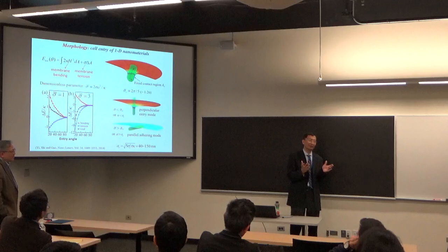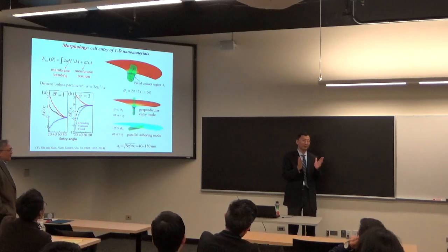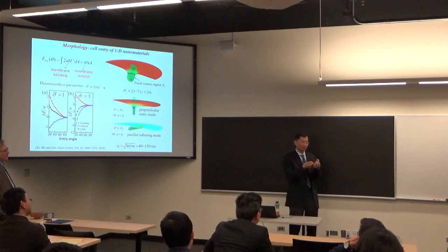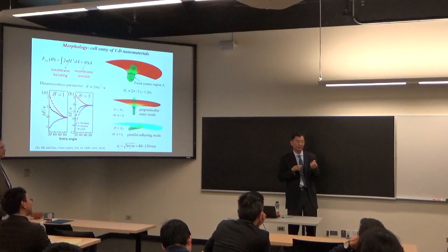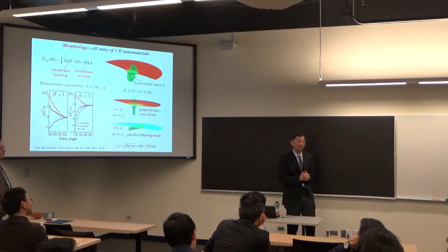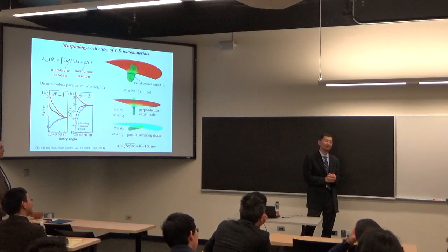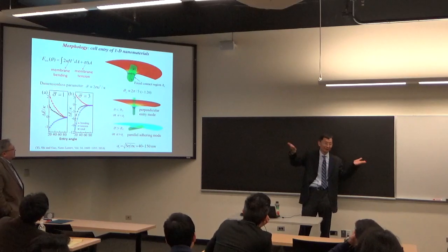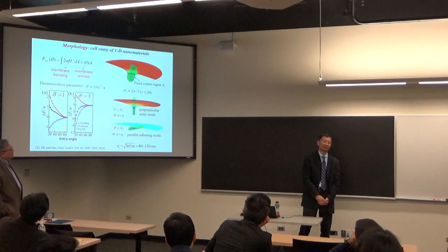The rotation on the fiber is almost dynamic. People have done experiments, for example, using biosuction experiments. You have a fiber poking out of the cell membrane, you increase the internal pressure, then that fiber suddenly snaps. That time scale is a fraction of a millisecond, very fast. But the contact area change by diffusion is very slow.